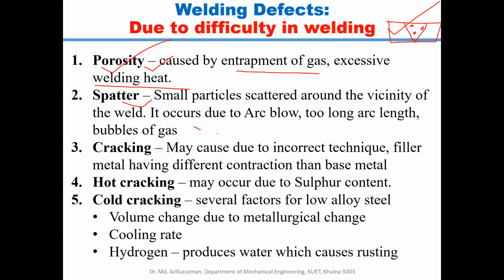And the spatter, like sprinkle, you already know that. And cracking may be caused by incorrect technique also, but sometimes it is very difficult to avoid, for example metals having different contraction than the base metal. Then the cracking will occur. And hot cracking may occur due to sulfur content. If the base metal contains sulfur, then metal sulfide will be produced in the welding zone, like the porosity, and metal sulfide actually acts as a defect.